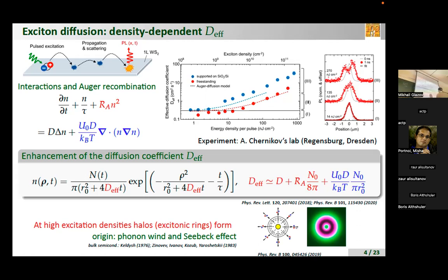The resonant Auger process is as follows. You have one conduction band, and here you have another conduction band. Actually, they have a bit of peculiar dispersion. And this band gap and that band gap are about the same. And then if you have two excitons like this, one recombines, and here the electron goes up. Our estimates show that it gives a reasonable value of the Auger coefficient.